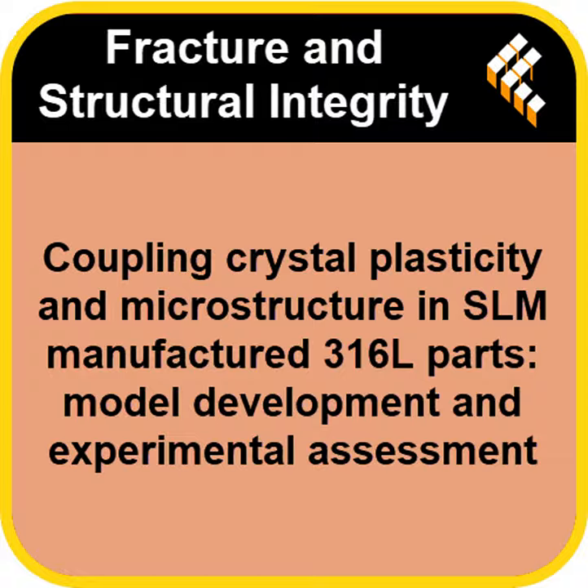It absolutely does. The thing that is hardest to manage, that big macroscopic residual stress, is surprisingly not the main driver of yield performance. The dominant factors are those microscopic barriers, the grain size, and especially the distance between those submicron twins. So if you're a manufacturer, you can stop spending a fortune on post-processing techniques, trying to bake out every last bit of residual stress.